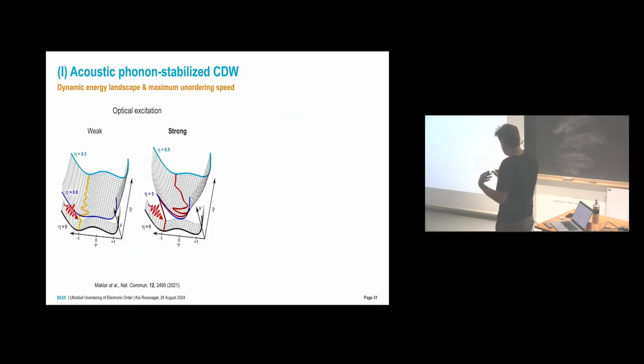Okay, here again, they have also illustrated this in a nice dynamic energy landscape picture. You do the excitation. If you end up with the double well potential still in your excited state, you will have some oscillation in this shifted potential. Or if you pump hard, you can really undo the lattice distortion excited here, and then you go to here, and now imagine a strongly damped oscillation, and you end up here, and this would be 1/4 oscillation period. This is the fastest time scale.